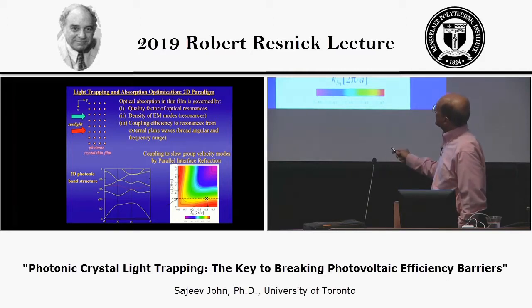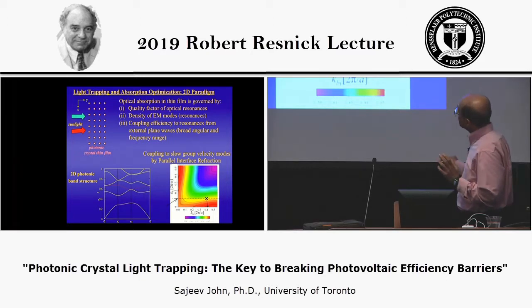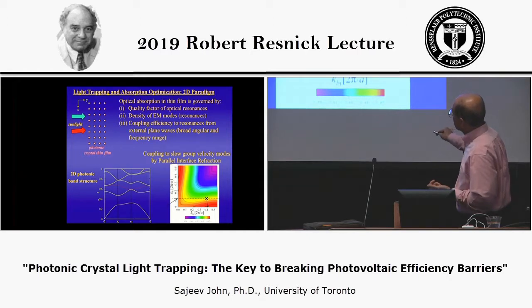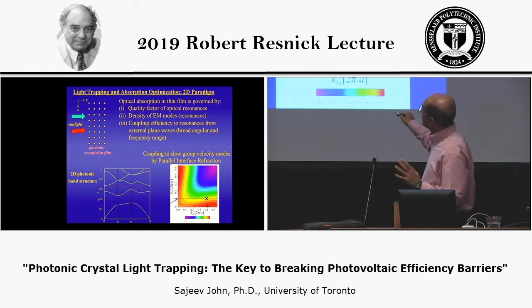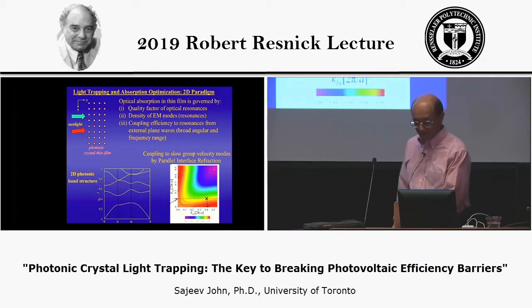These are the slow light modes that I'm referring to. And so when sunlight impinges on this structure, the law of refraction is actually not as simple as something like Snell's law. It depends on the shape of the surfaces of constant frequency in the structure. And in this case, we can show that a light beam with an initial wave vector coming in like this would find the isofrequency surface associated with the incident frequency and then propagate in a direction that is normal to these surfaces. That's the direction of the group velocity. So it would actually be propagating nearly parallel to this interface. And because of this flat dispersion relation, it's bouncing back and forth many times in the vertical direction here. So that's part of the mechanism behind what I'll be describing to you.